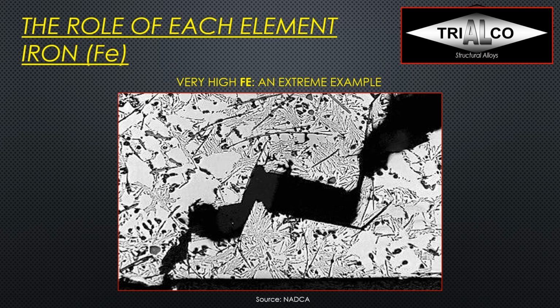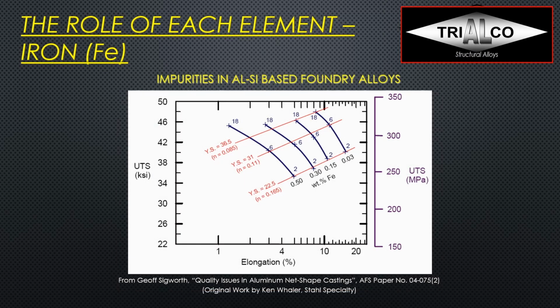And so if you have any stress riser, the crack will just go straight through your casting. If we look at what iron really does, a lot of studies have been made, and I'm showing here a picture from Jeff Sigworth's study, a couple of years old, but that was a very nice demonstration. We can see it started with 0.5% iron, and we have of course a trade-off between elongation and strength, so we move up the curve depending on how long we age, and we see we are on one curve and we just have this trade-off. If we want to move up and go to a higher curve, we have to reduce the iron.